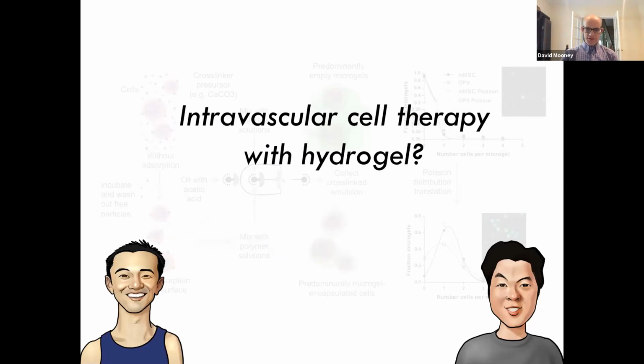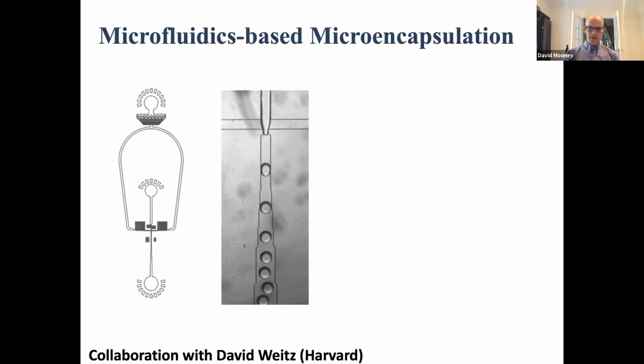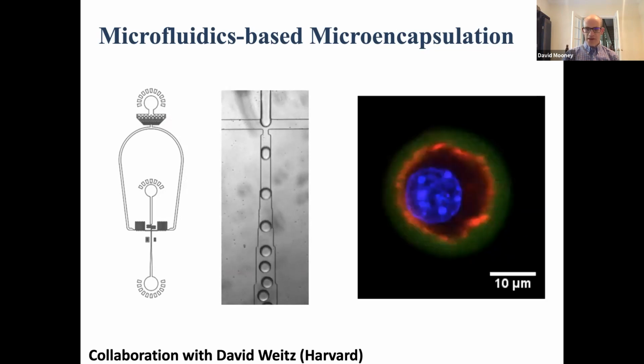And this work is done by Jae-Won Shin, who's now running his own lab at the University of Illinois, and Angela Mao, who's a postdoc now over at MIT. The approach they took, in collaboration with David Weitz, was to use microfluidics. So the idea is we have a solution of cells with our alginate solution. We create droplets where we then get gelation of the hydrogel around the individual cells. And we get a very thin layer of hydrogel surrounding each individual cell. Here we're just looking at an image of an individual cell. The blue is the nucleus, the red is the actin, and the green is the hydrogel halo around that cell.